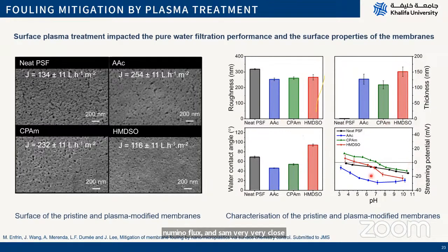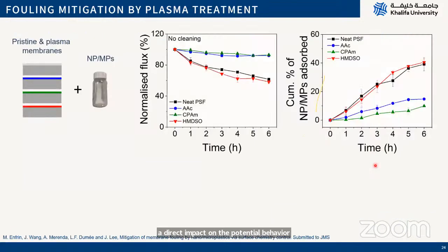However, despite having a similar morphology, a similar roughness, and adjusting the flux to be in the same range, we found that the surface charge, obviously the streaming potential, was very different. And that makes sense. The polymers we are adding on the surface of the membrane by plasma deposition here are very different. So we had the acrylic acid membrane, which was always very negatively charged across the broad range of pH. We aim for 6 to 8, obviously, but we could get the amine-rich membrane to be much more positively charged. So we can have a direct impact on the potential behavior, adsorption, and maybe even transfer of some contaminants across the membranes.